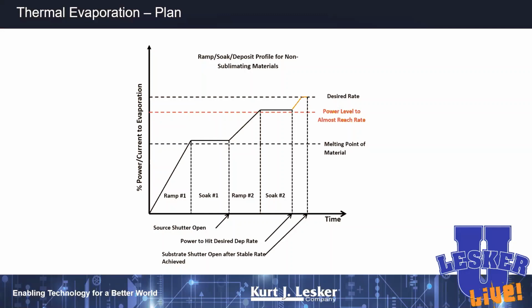Again, you never want to use more power than you need. There's no reason to go to a deposition rate or an equilibrium vapor pressure over 10 to the minus 2 torr. You will not like the morphologies of the films that you get.